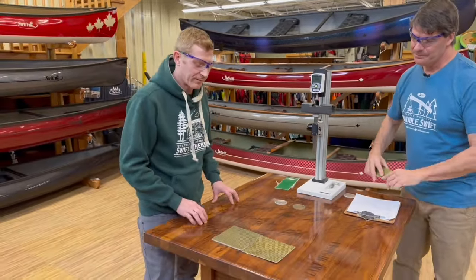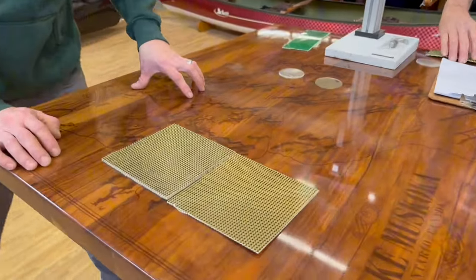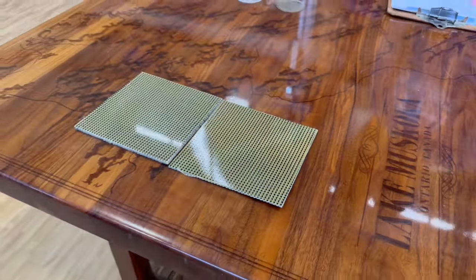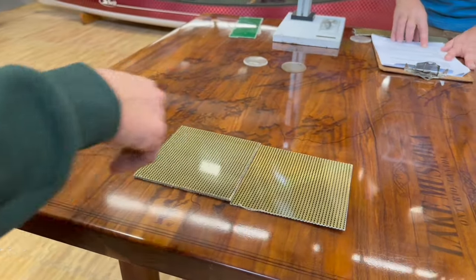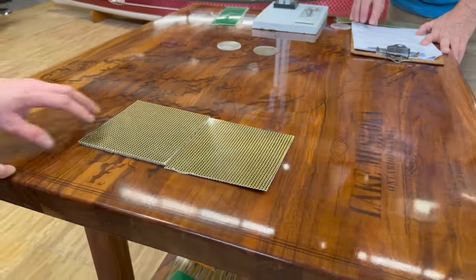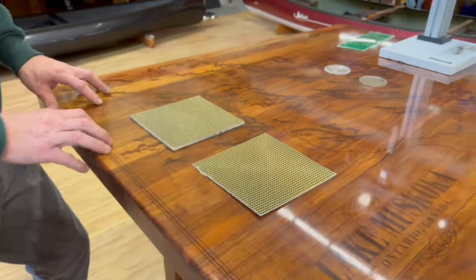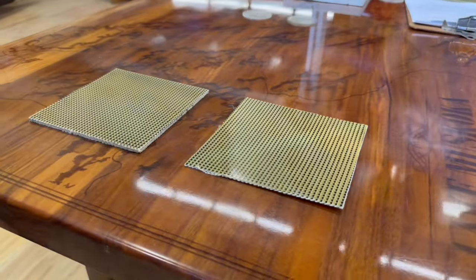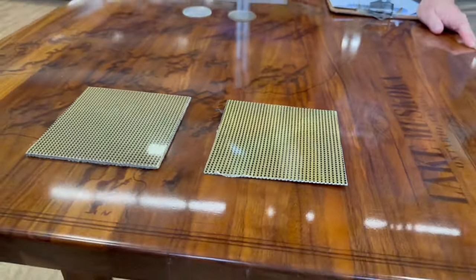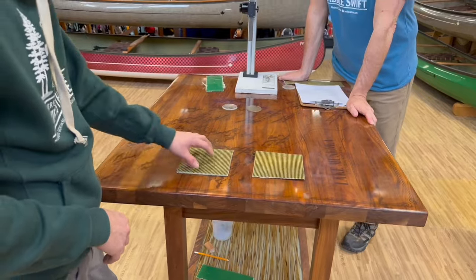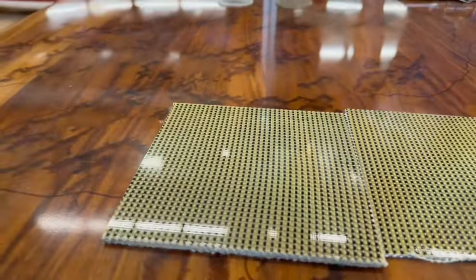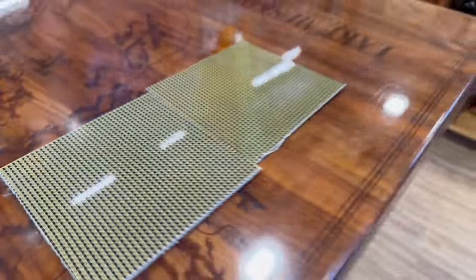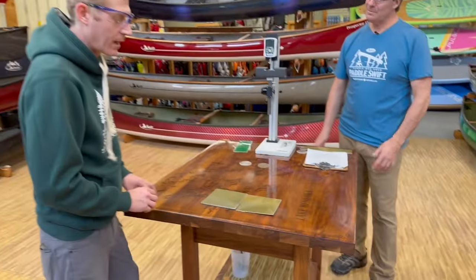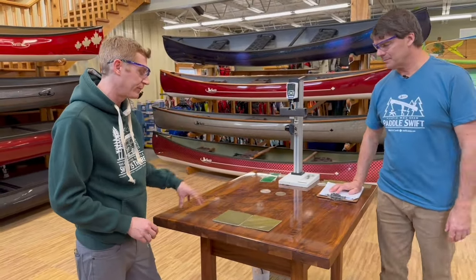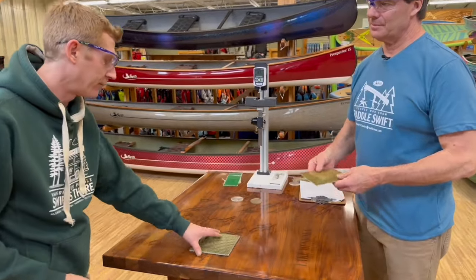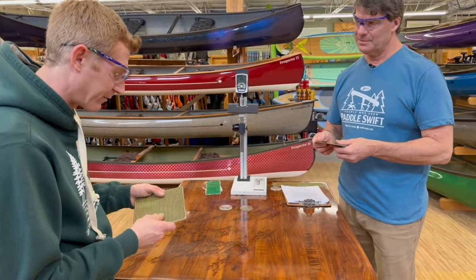To get started, we've done some testing. This should replicate about 6 months of direct sunlight. If we look at one of them, we applied two pieces of tape before we put these under UV lights. You can see this has our UV shield and this is our traditional gel coat. In the traditional gel coat, the line where we covered up the material with tape is quite apparent. In our UV shield, it is quite reduced. You really have to look hard to see it. We're super excited about this, as Kevlar can be a UV unstable material sometimes, but with our UV shield, it's going to be totally protected. And this aerospace coating that we're using here is just absolutely incredible.